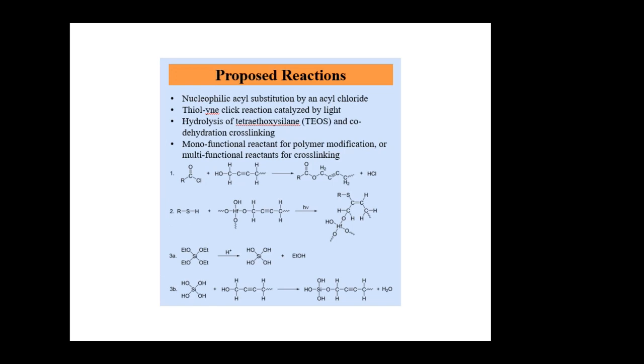We chose 3 reactions to try. First is a nucleophilic substitution with an acyl chloride, which reacts with the OH groups in the polymer and releases hydrochloric acid. Second is a click reaction between a thiol and the triple bond in the polymer, which is catalyzed by light. Third is the hydrolysis of tetraethoxysilane, otherwise called TEOS, and subsequent dehydration reactions with the OH groups on the polymer.